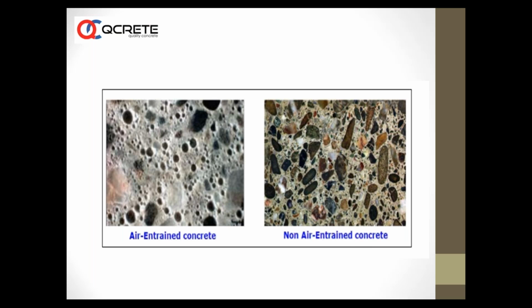One of the most important points which we need to remember when we are using air entraining admixture is that the amount of air entraining admixture should not entrain air beyond 6%. That is the specification for usage as a structural concrete. If you entrain more than 6%, the effects will be very big. Actually, every 1% of air reduces 5% of strength. So we need to be very careful, considering the benefits we talked about already.